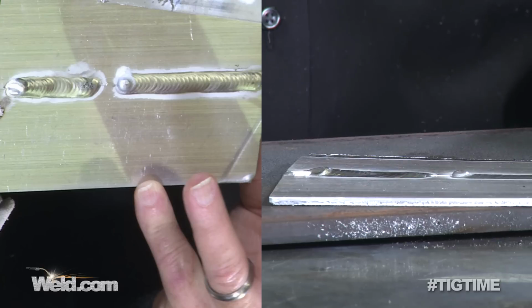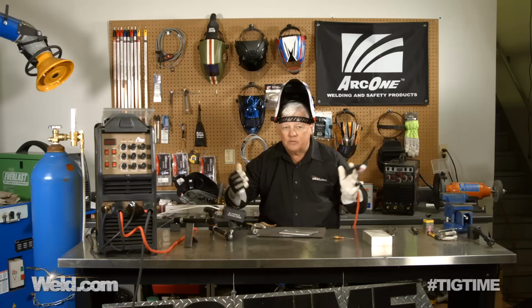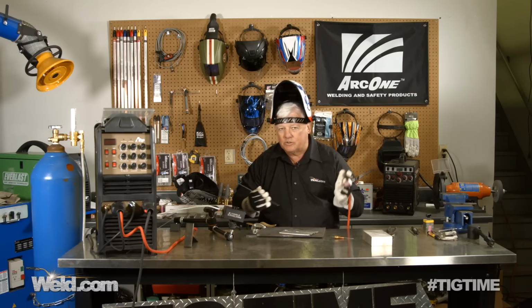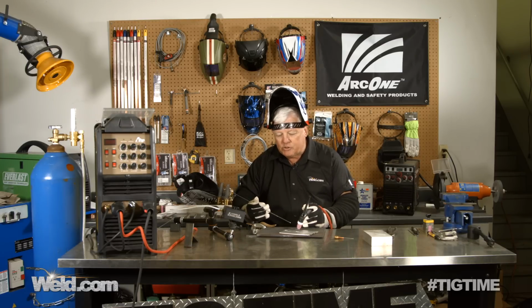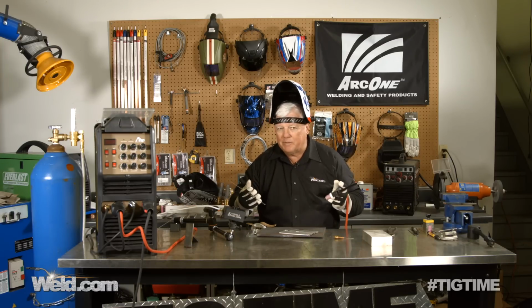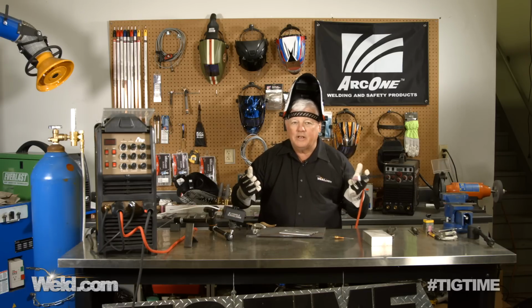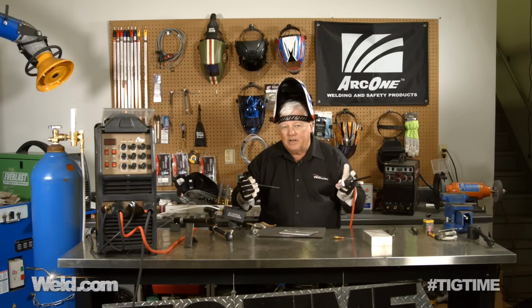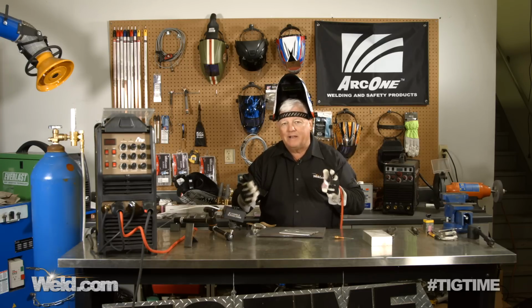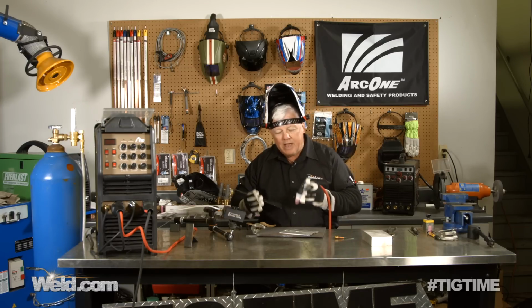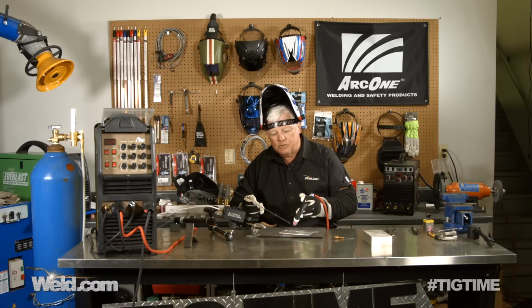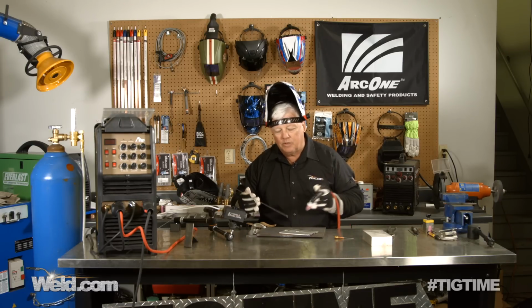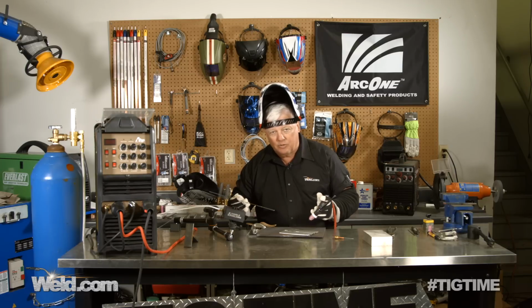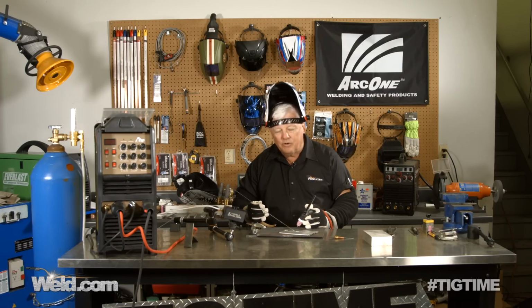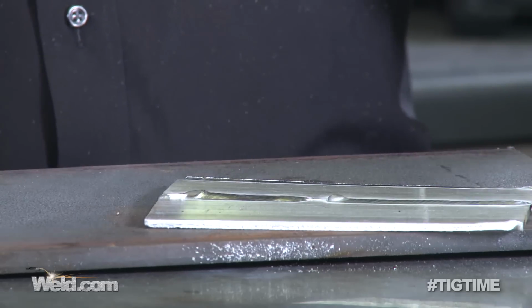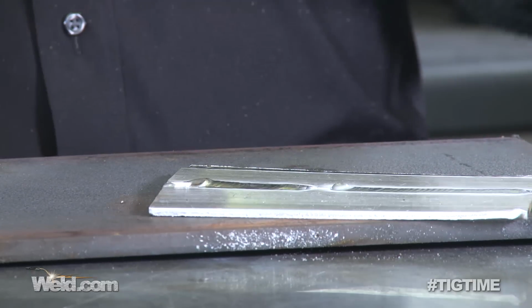If you're adding more cleaning and it's bombarding your plate, it's wasted energy, it's gonna trash your tungsten. So I did the 3 inches, and then I had it set on 50% balance. And theoretically, that's the optimum setting. Well, it isn't. So just know a balanced wave is not the way to go. What happens is you start losing stability. If you start losing stability because you got all this cleaning action going on, you don't have any welding action going on. So it's actually a dirtier weld. The cleaning action is hitting a broader region, and you just don't have a pretty weld.